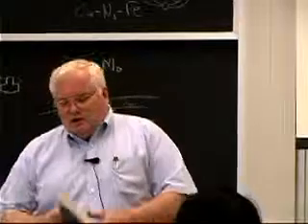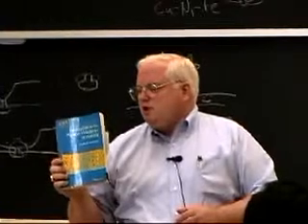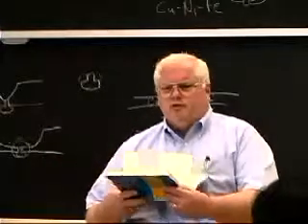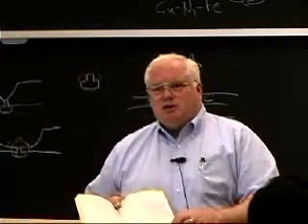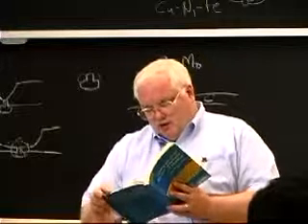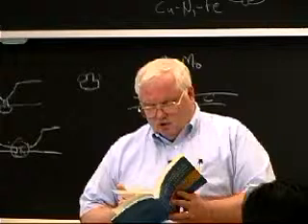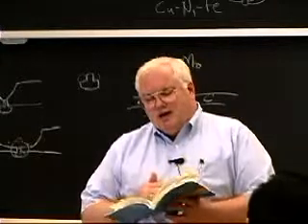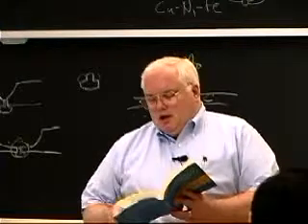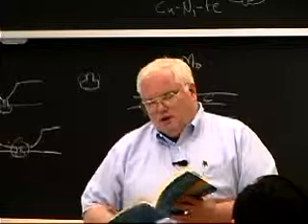That particular sheet came out of the back of this book, Introduction to the Physical Metallurgy of Welding by Kenneth Easterling. This book also has this story, which I think I copied for you, the case of the Alexander Kielland disaster. This is the offshore platform in the North Sea. On March 27th, 1980, the Kielland, at 6:30 p.m., tipped over in the North Sea. 123 out of 212 people on board died. It was a hydrogen crack at a 6mm, a quarter-inch fillet weld. That started a fatigue crack that got to be tens of feet long before the thing finally came apart.